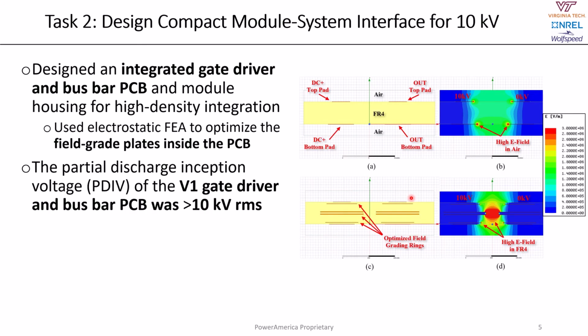The second task is to look at the design and test of the compact module to system interface for these 10 kV power modules. And so on the right, we show a 2D cross-section of a PCB, and the yellow is showing the FR4, and the top and bottom has copper traces. And when you apply 10,000 volts between these two traces, you see that the peak electric field strength in the air exceeds the 3 megavolt per meter limit of the air.